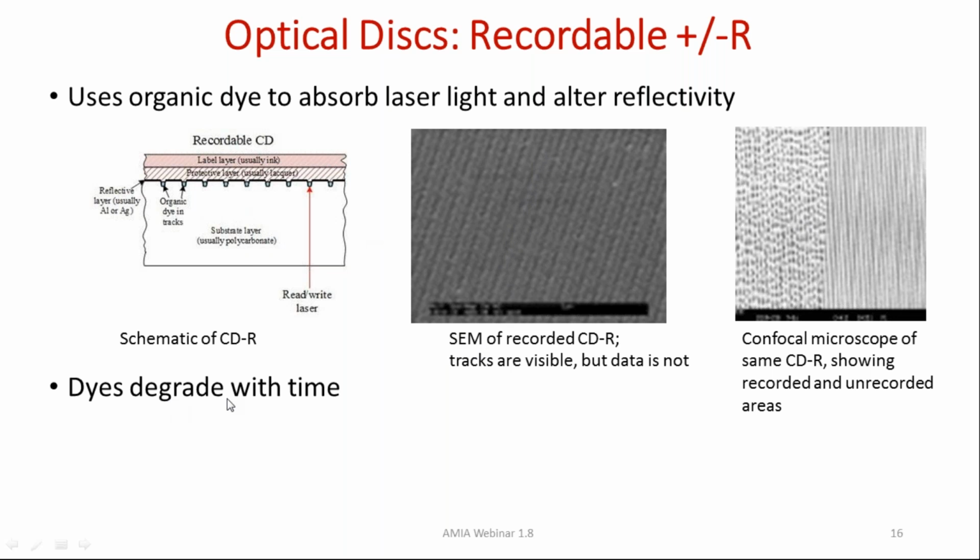But these dyes, because they are carbon-based, they are degradable, biodegradable, and they do degrade with time. And of course, they change as a function of light, which means if you leave these discs out in the light, the data will be lost. They also change with temperature and humidity, so you want to store them cool and dry, ideally, or a medium humidity, 40 to 60%.